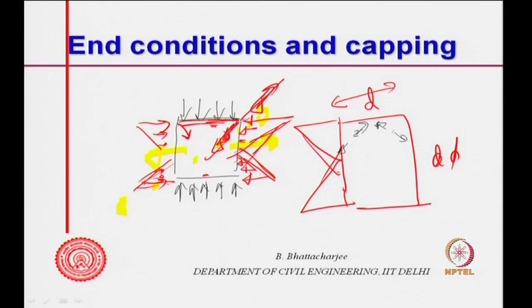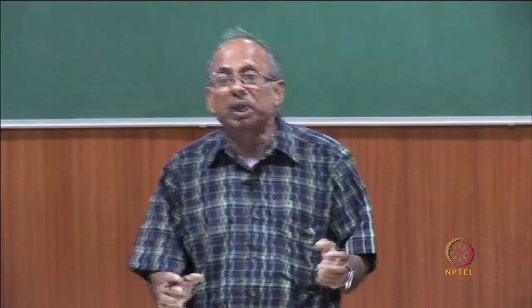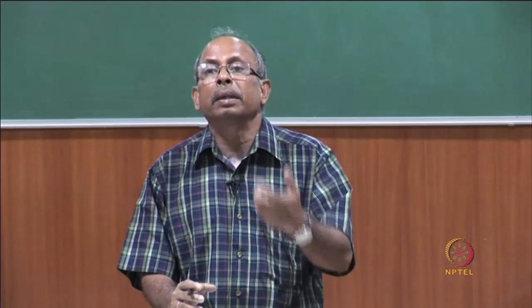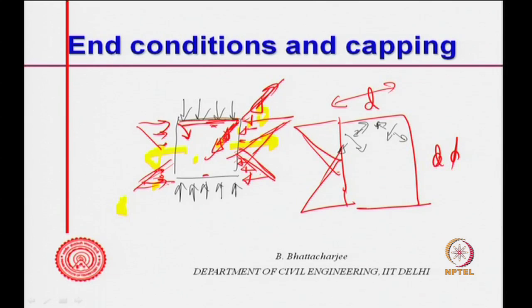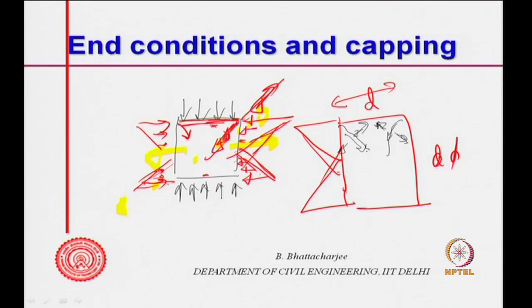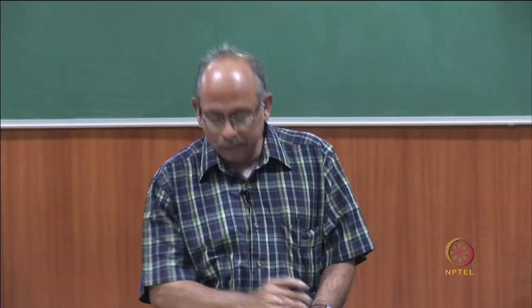So, tension acts like this because compression is along this direction, the net force being the resultant of the frictional resistance and the applied load. So, the net compressive force will be along this direction, which means the transverse tensile force, because of Poisson's effect, will act like this. So, you have a crack in this direction and in this direction. This is called the Platen effect.